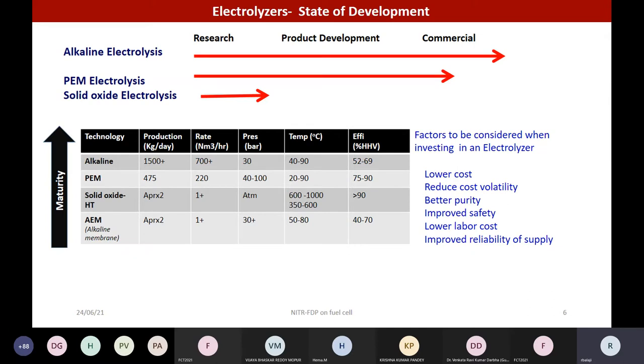In that case, this polymer electrolyte membrane based technology will withstand high temperature and high pressure, because of the high mechanical strength of the membrane, which will withstand up to 100 bar pressure, so that the hydrogen can be pressurized and used for any other purpose. Whereas in the case of alkaline, people are using only asbestos based separators, which may not have high mechanical strength to withstand high pressure. That's why the development of high pressure electrolyzers using alkaline based systems is not that mature.